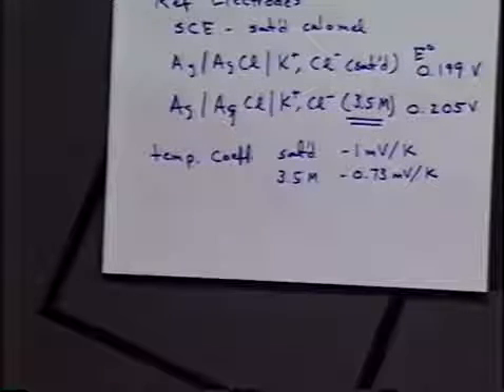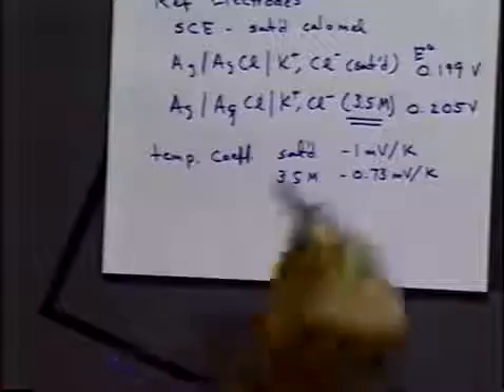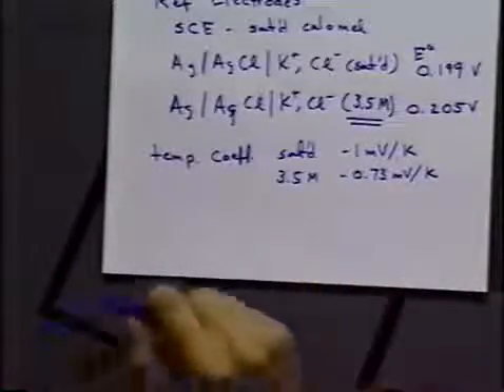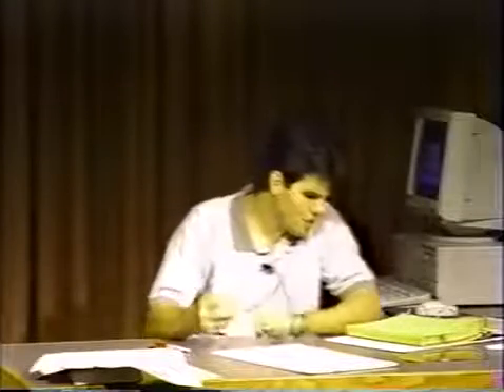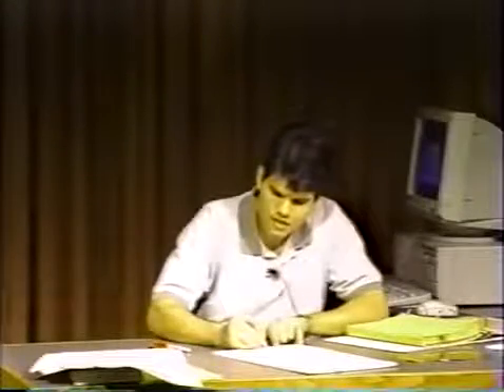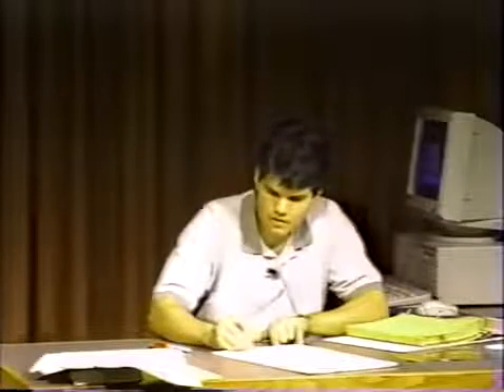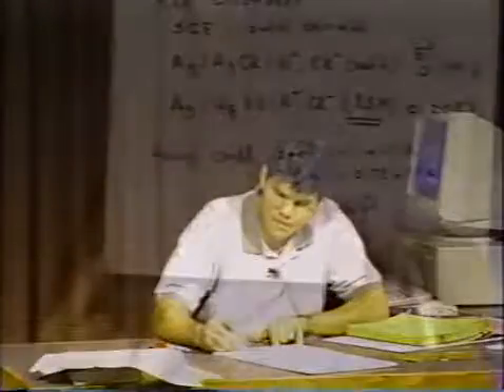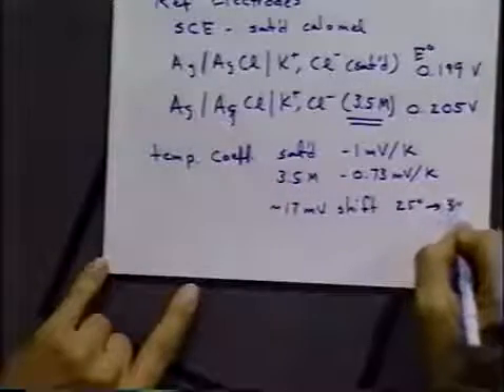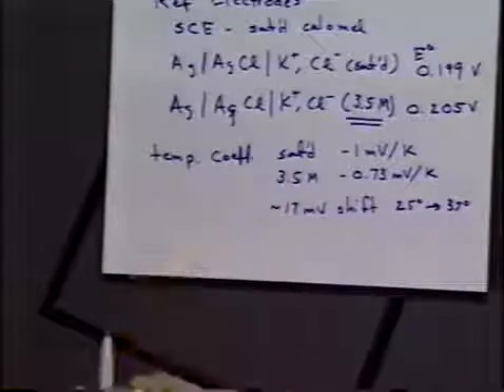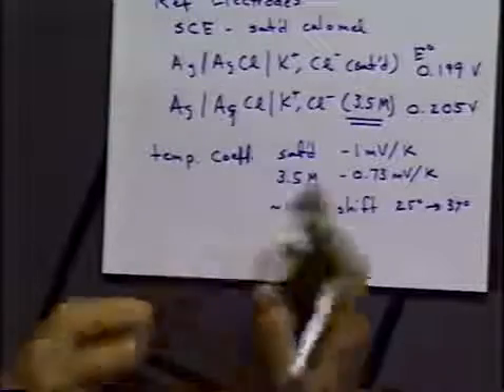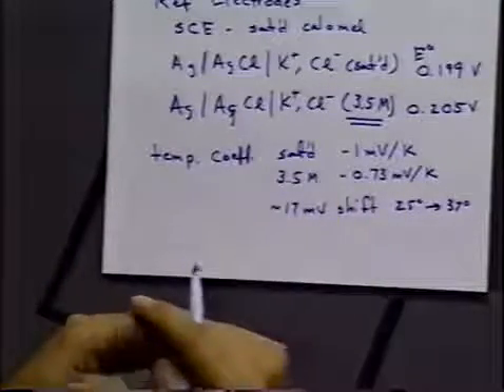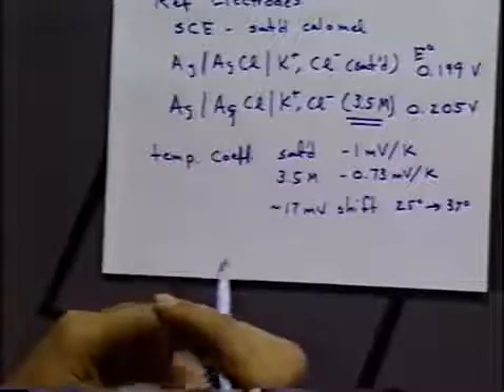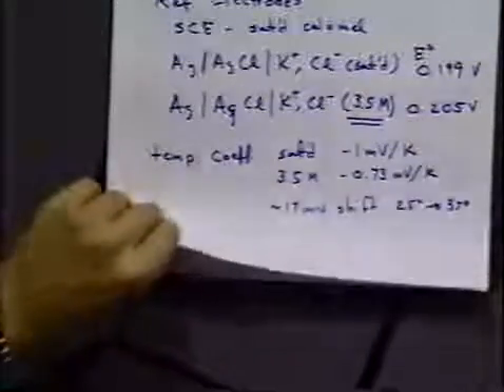For example, a lot of times people use silver chloride systems in, say, living animals where the temperature might be 37 degrees centigrade. That corresponds to approximately a 17 millivolt shift from 25 to 37 degrees C. And so the saturated silver chloride is not as useful as the 3.5 molar ones. It has less of a shift in potential with temperature. The silver chloride is a very common one.